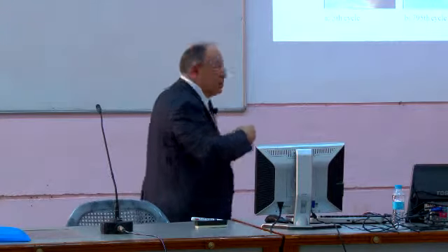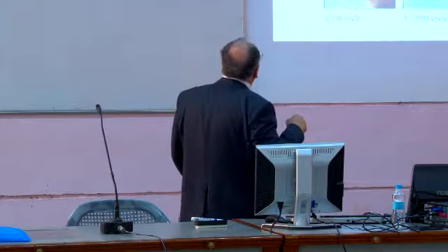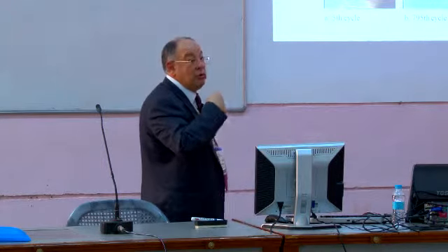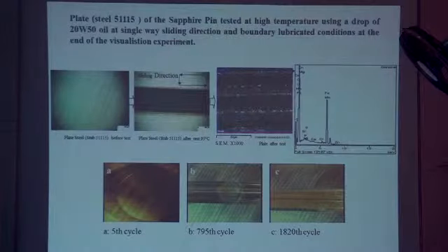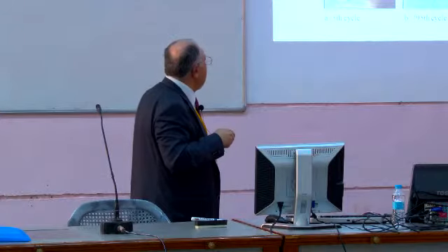Yeah, this is the test. I'll show you the visualization shortly, it takes a few minutes. It's a long test because the usual formal condition test takes 42 minutes to obtain layers. So you see the pin material, new one and used one, by SEM and X-ray, and we have additive layers on the surface. This is the beginning, middle, and end of the test.